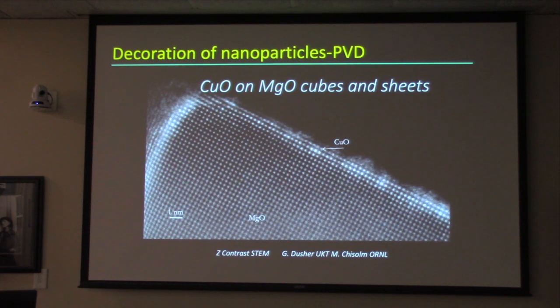In the story, you can look it up. The patent, it turns out, for methane to methanol originally was zinc oxide decorated with copper by the Japanese. And then they had to introduce some nickel because it started to poison. But I wanted to get my hands on using things that we can make easily. So we decided to put some copper deposit on the surface. And the one thing I want you to notice is the highlighted things there, that turns out to be the copper. We've managed to put copper substitutionally into the surface, only in the first two layers.